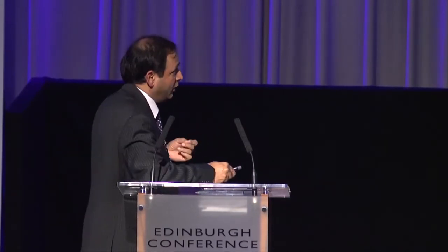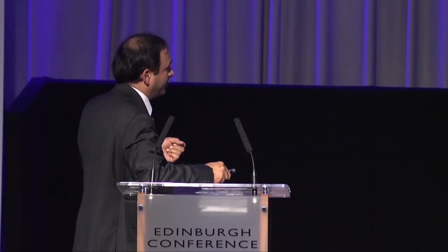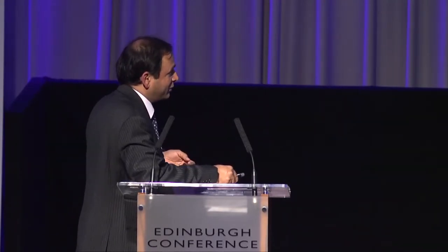But obviously, just to let you know the state of the art of these technologies and how they're moving, you can see that 20.3% cells were made on rigid glass substrates, which have now been surpassed, strangely, by a group at EMPA in Zurich. This is now a new established world record, with 20.4% cells made on polyimide foils. And this is something very amazing, because it was believed that these polymer foils would not have better efficiency. That was a kind of myth we had, but it's turning out very different with this kind of material. So you need the right kind of expertise and knowledge in order to prove the point. And this is where I see a match of R&D and industry has to come. So this is a recent development. I think in the last month it has happened.